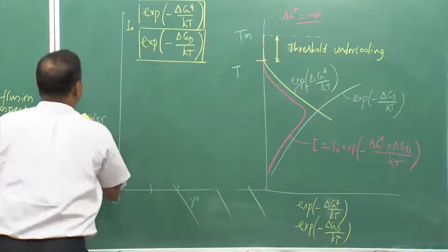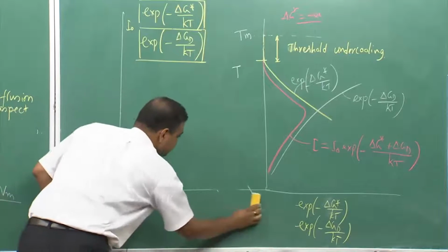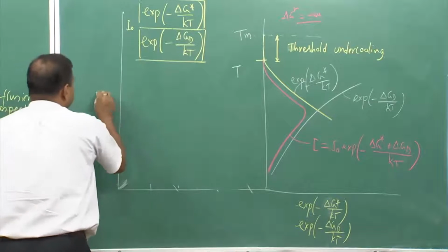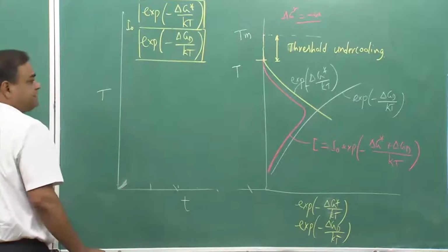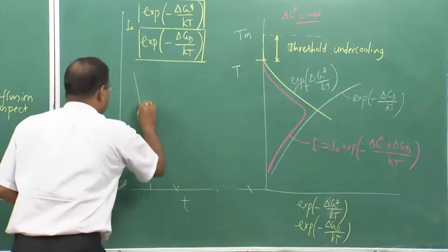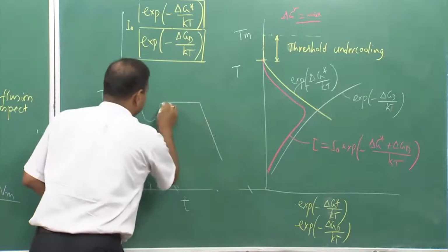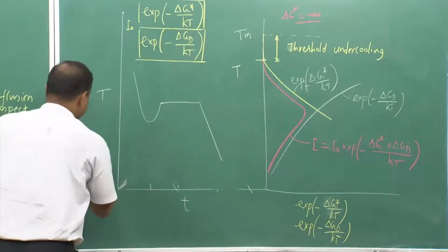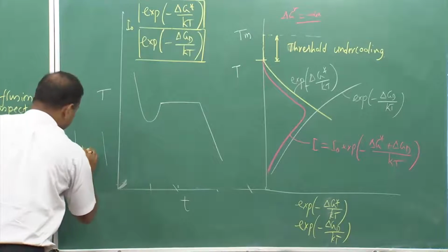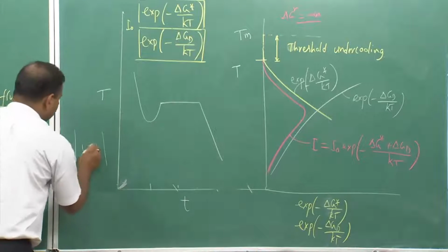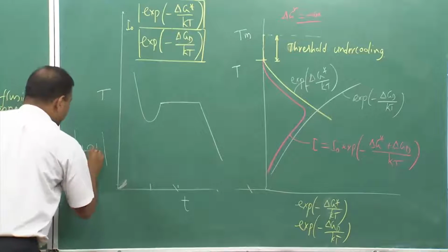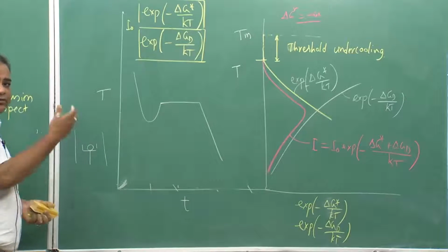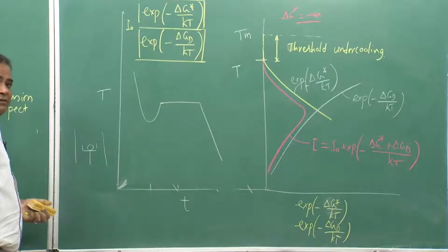is not possible. Now, this particular thing we see when we solidify a pure metal. We try to see the cooling curve of a liquid metal. The cooling curve is nothing but a temperature-time plot. If it is a pure metal, we sometimes see this kind of variation. The experiment is pretty simple. I have a furnace, and in the furnace you keep a liquid metal, and I put a thermocouple here and start measuring the temperature as we cool down the liquid metal.